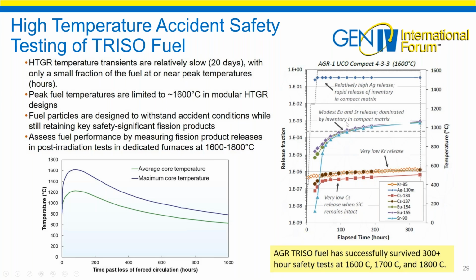The europium and strontium release, there is some, but it's dominated by the amount that's in the compact matrix. It's not pure graphite. There are other materials in there, so we will see that. And silver is released, and silver is not a dose that we worry about with the public, but we do have operational concerns for technicians. But again, silver can be trapped by cold traps. It's just a problem if a technician has to go into a part of the reactor coolant loop and do some work. So again, we ramp up in the temperatures and we hold it there. Now notice that we did our test for 300 hours, which is, we're basically saying, for instance, that temperature goes up, and that for this accident, we envelope it at 1600. So obviously, we're having a longer temperature than we would ever have in the reactor itself.